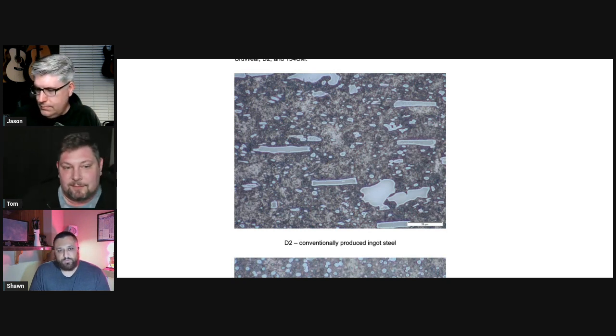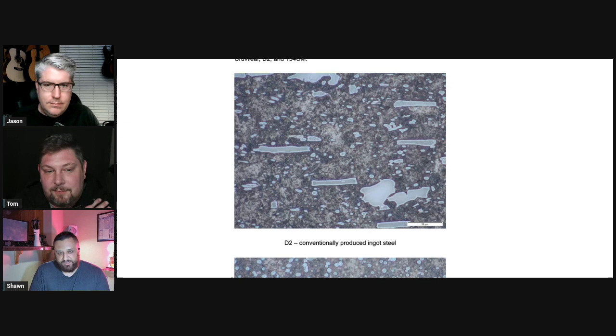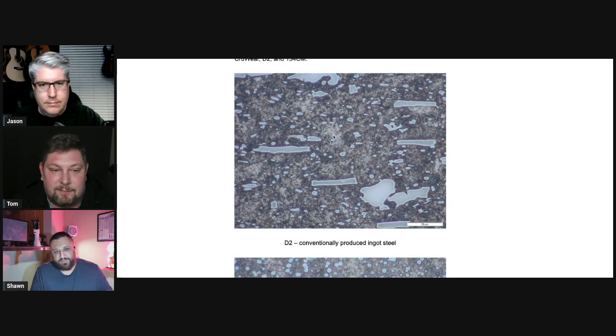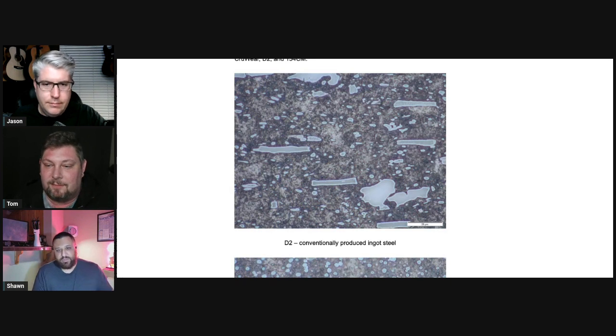And so what we're looking at here is you see all this busyness and you're like, I don't understand what I'm looking at. What you really need to look at, what this micrograph is trying to highlight, is they take a surface, they polish it down, and then they etch it with a type of acid that eats down the matrix and reveals these carbides. All steels are a mixture of carbon and iron, but you're usually going to have carbides inside of these knife steels that we like to use.